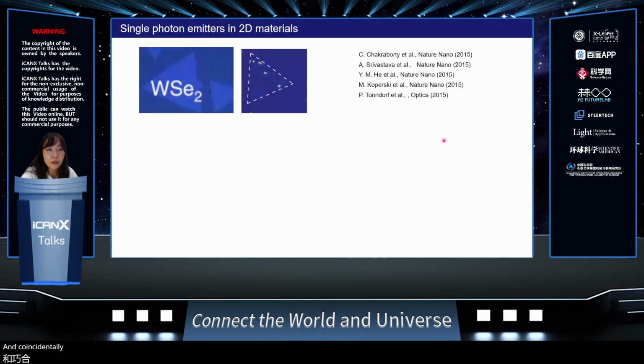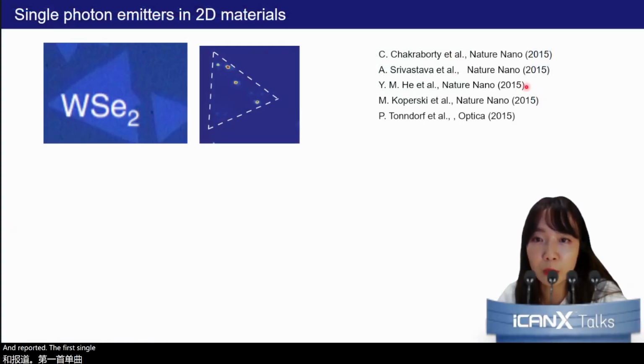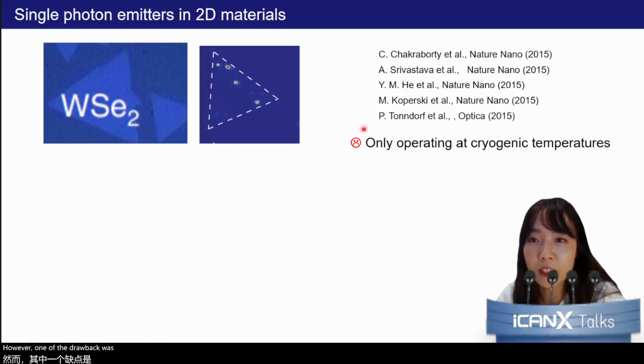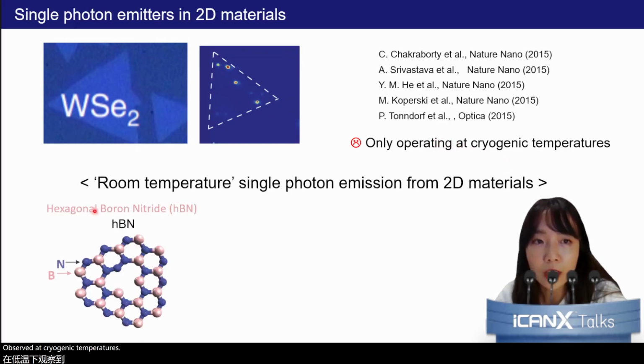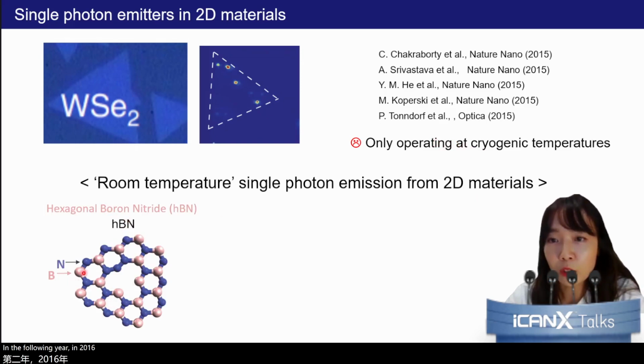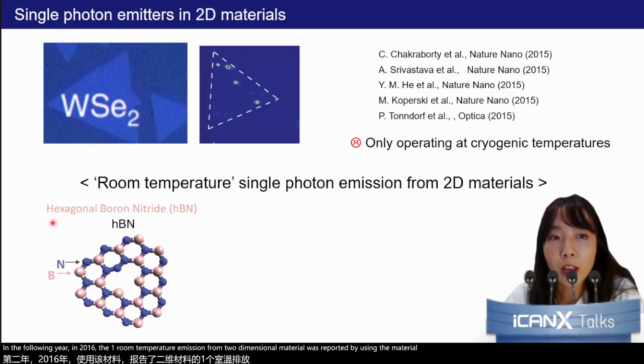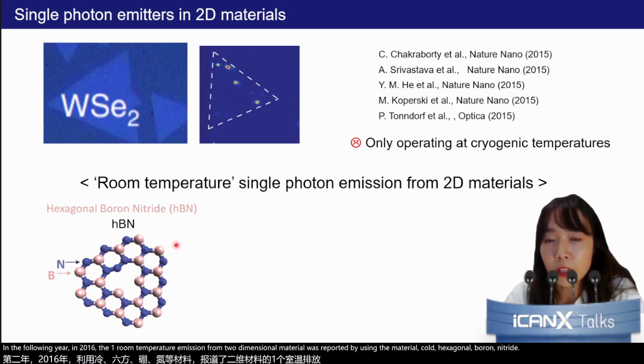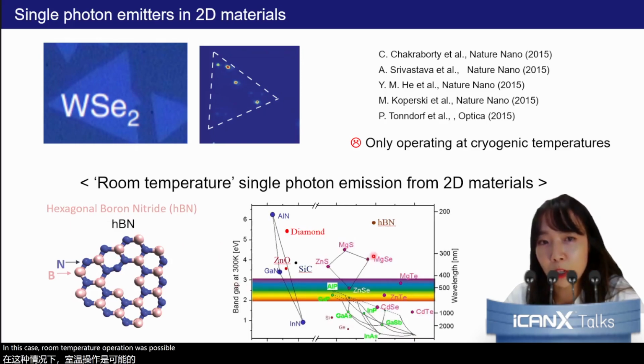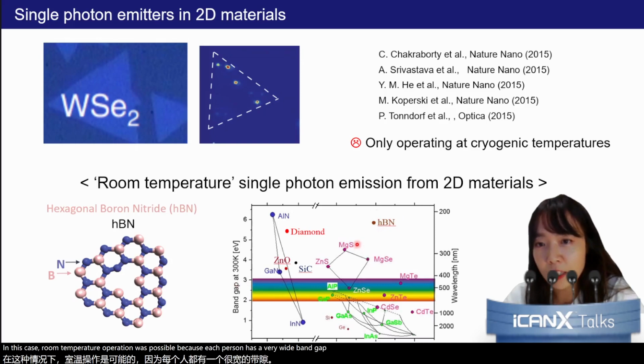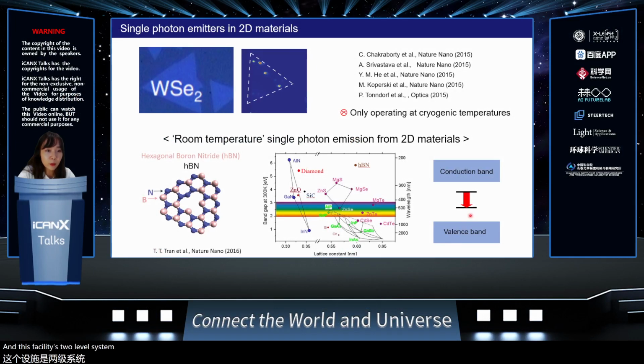Coincidentally, five papers were released in 2015 reporting the first single photon emission from tungsten diselenide. However, one of the drawbacks was that this emission could only be observed at cryogenic temperatures. In the following year, 2016, the first room temperature emission from a two-dimensional material was reported, using the material called hexagonal boron nitride. In this case, room temperature operation was possible because HBN has a very wide band gap, as illustrated in this diagram, and this facilitates a two-level system deep within the band gap.